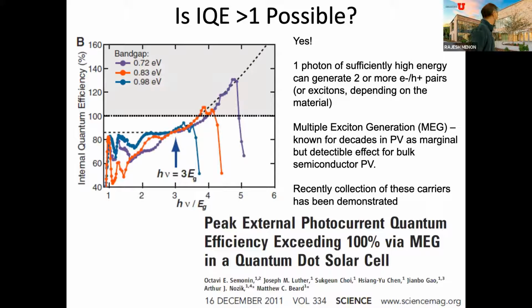In a very important paper, a little more than 10 years ago, this was actually shown. And the idea is that 1 photon with sufficiently high energy, so blue or UV or something like that, can generate 2 or more electron-hole pairs. So instead of just creating 1 electron-hole pair, you have enough energy to create more than 1. And we'll see how that is. This phenomenon is called multiple exciton generation, or MEG. It has been known for several decades in photovoltaics as a very small effect, but not very efficient. It can be done with much better material science, which is what they did in this particular case.